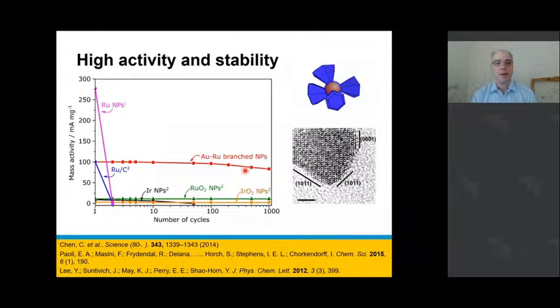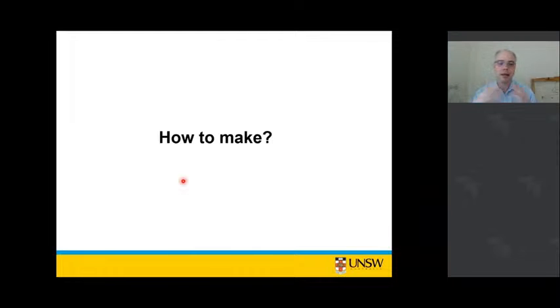And the nice thing, if we go back and have a look at these kinds of plots that we can do in terms of looking at how active and stable different catalysts are, is that in terms of where these branch ruthenium systems actually sit on this plot, we are starting to fill some of this empty space, which is nice. As I said, we have our good activity because we've got an oxidized ruthenium catalyst, but when we cycle, say even up to 1,000 cycles, we're still getting good retention of the initial activity. So, as I said, they're really nice catalysts, these branch ruthenium structures.